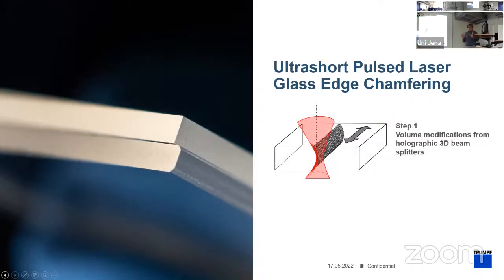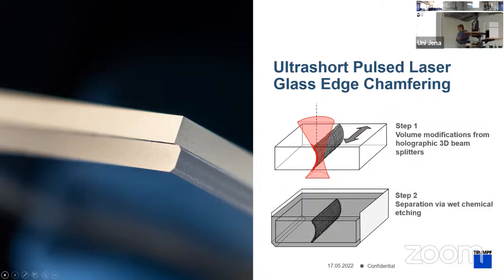So it is possible to compensate, and it is possible to rotate the beam axis with respect to the optical axis of the system. But first, I want to step into another approach for generating even more complex shapes. This is that you inscribe volume modifications from holographic beams, 3-dimensional beam splitters, so 3-dimensional multi-spot arrangements, and then use a second step for separation via chemical etching. So this is no longer a zero gap and helps with much finer contours and more complex shapes.